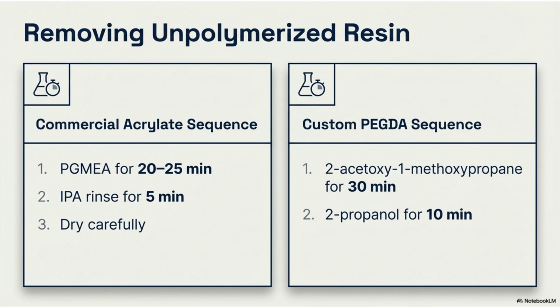To remove unpolymerized resin, commercial acrylates require development in PGMEA for 20 to 25 minutes, followed by an IPA rinse for 5 minutes. Custom PEGDA resins use 2-acetoxy-1-methoxypropane for 30 minutes, followed by a rinse in 2-propanol for 10 minutes.